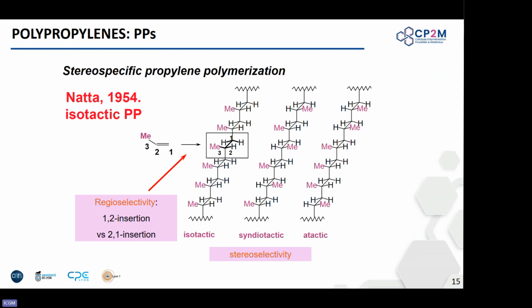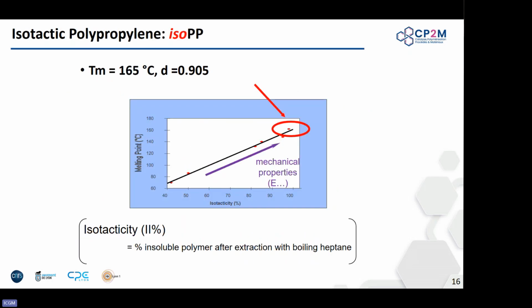Because you have this methyl, of course, this governs the chiral center, and then you can have isotactic or syndiotactic or atactic. And the big contribution to the Ziegler-Natta of Natta is isotactic PP, just so you know. So Ziegler is more responsible for the discovery of PE and that type of thing, and Natta, because he used alpha-TiCl3, so titanium at the oxidation state 3, he discovered that you could get this isotactic PP.